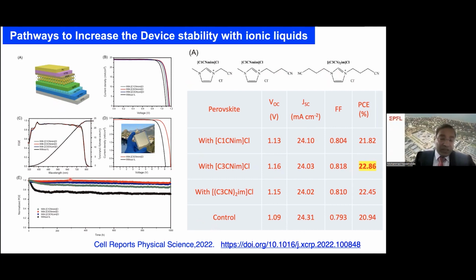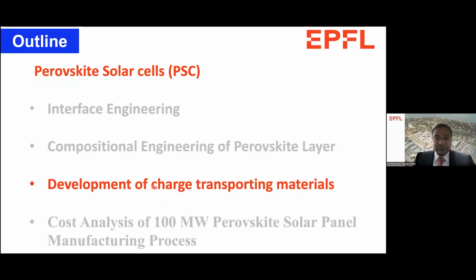And if you look at the stability, since our focus is enhancing the stability of these materials, we always compare with the reference, that's our reference sample under similar conditions, and using these remaining 3 ionic liquids, the best one is with the cyanide and 1 long chain containing ionic liquid that gives you more stable performance compared to the remaining 2 other ionic liquids.